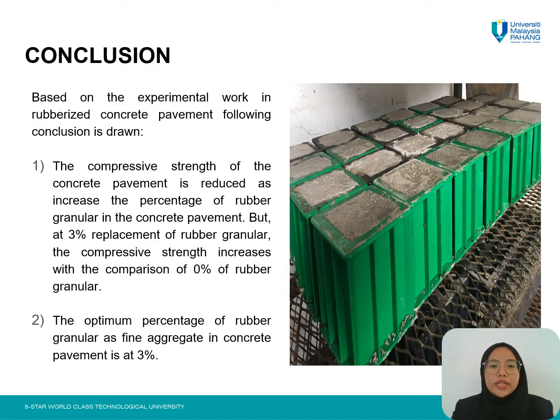So the conclusion: the compressive strength of the concrete pavement is reduced as the percentage of rubber granular in the concrete pavement increases. But at 3% replacement of rubber granular, the compressive strength increased in comparison with 0% rubber granular. The optimum percentage of rubber granular as fine aggregate in concrete pavement is 3%.